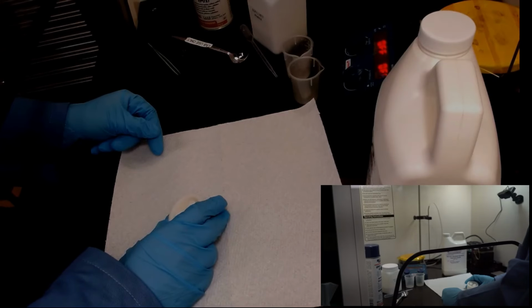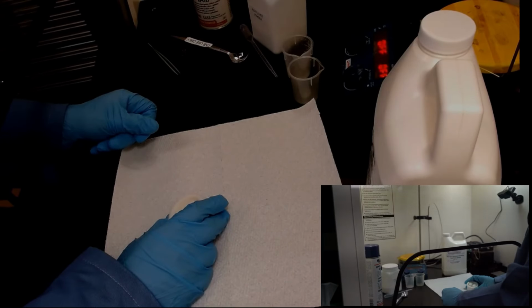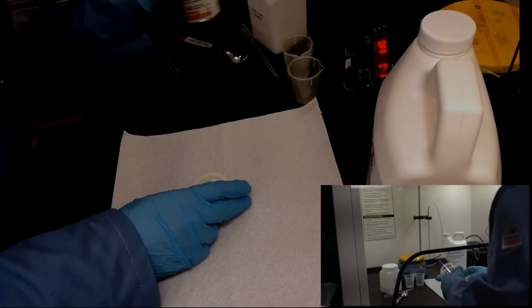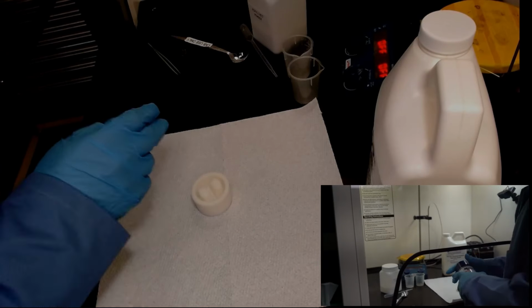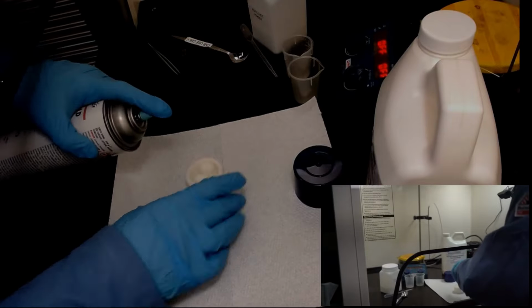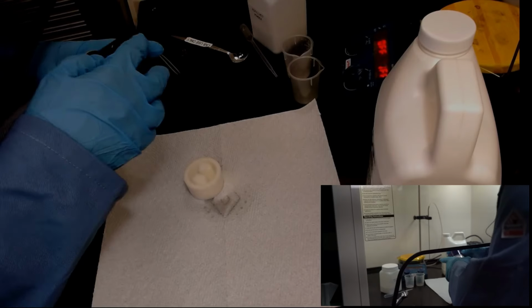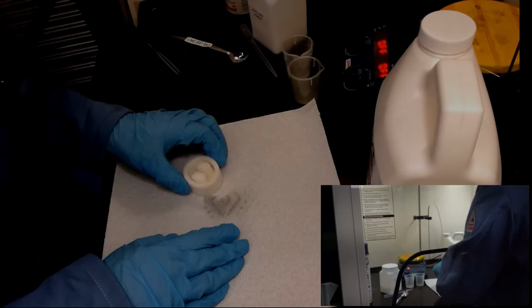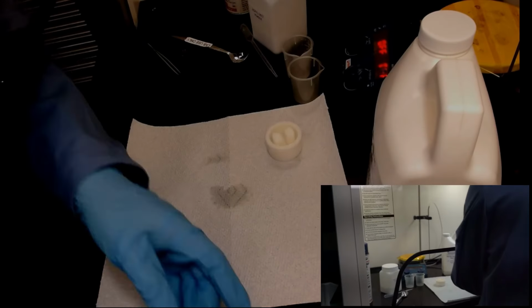So now we're over at the wet bench, and the next step is going to be to actually take the sample and put it in the mold so that we can embed it. We start with mold release spray so that it doesn't stick. This is just a standard epoxy mold release. It works just as well for acrylic. Shake off any extra.